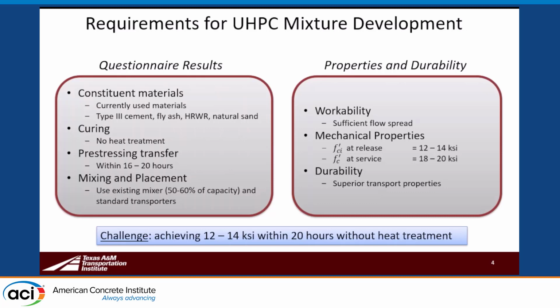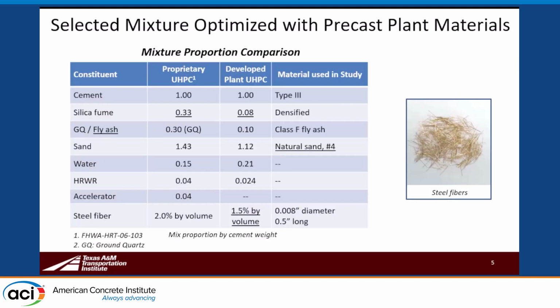So the big challenge here, which might be a little different than some projects, was to get the high early strength needed for release without heat treatment. This is a look at the proportions of our mixture. You see the constituents in the left column. The proprietary UHPC, which is pretty well known, is listed here, based on proportions that we got from an FHWA report. And then our UHPC mixture that we felt worked well overall is listed here.